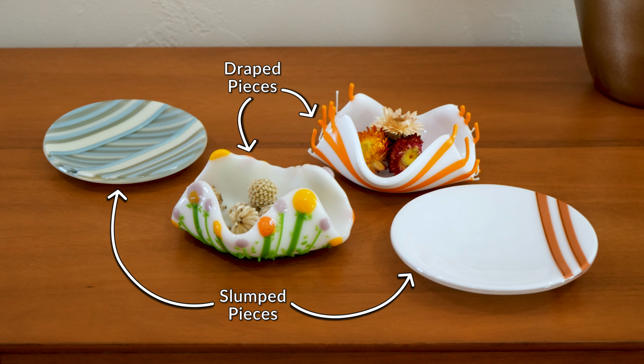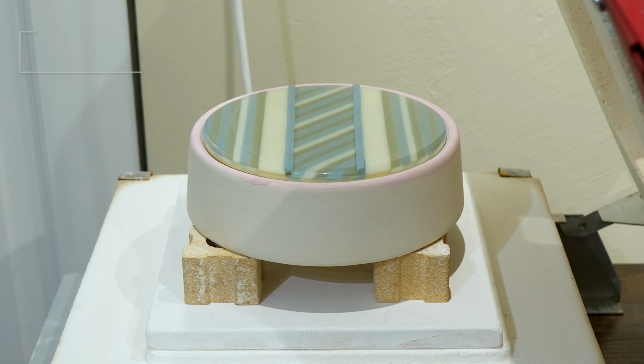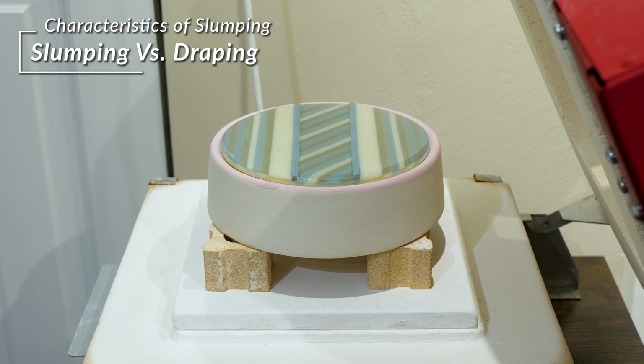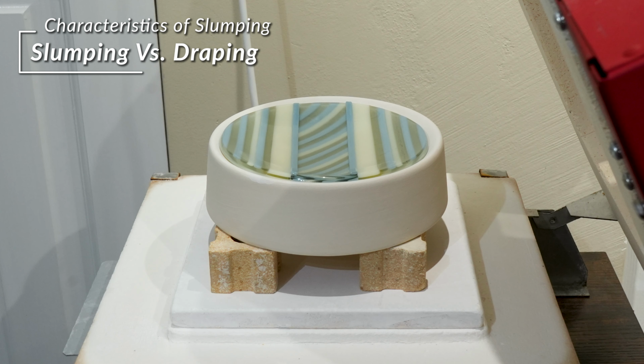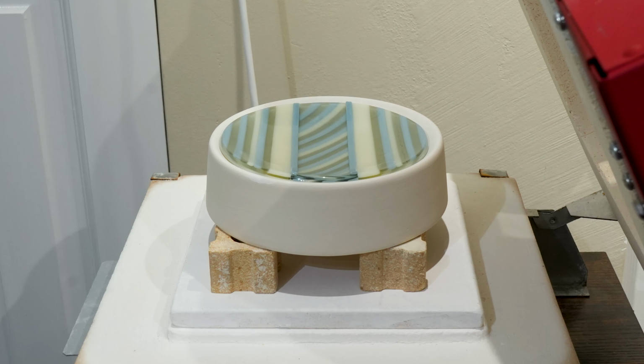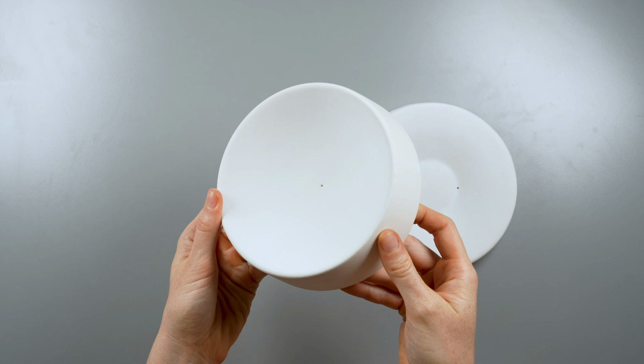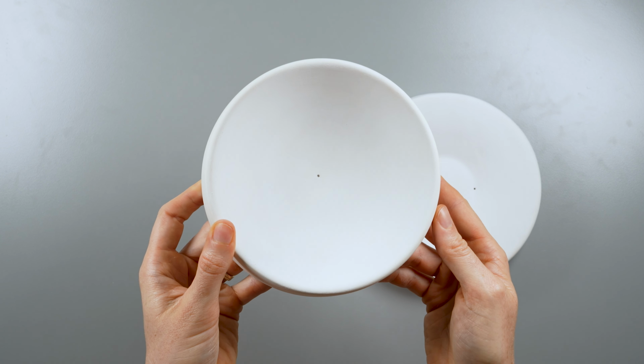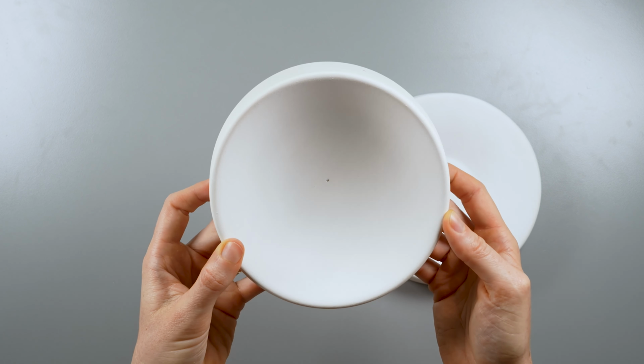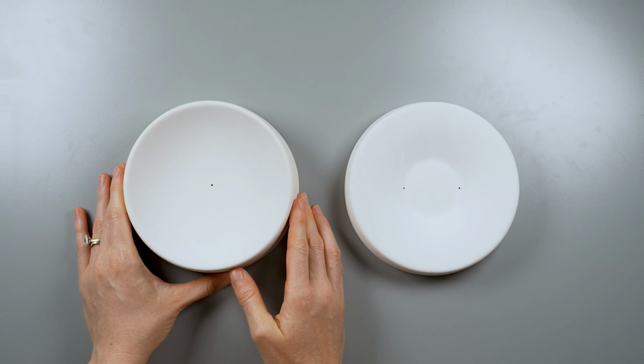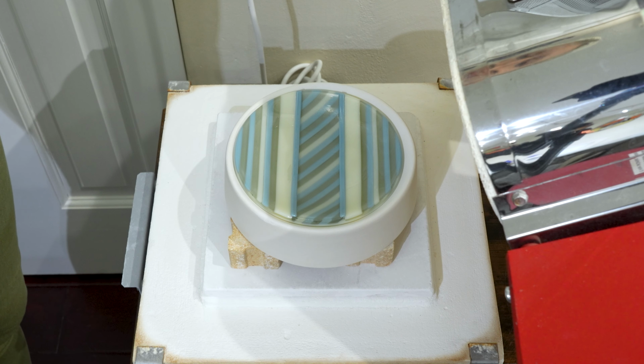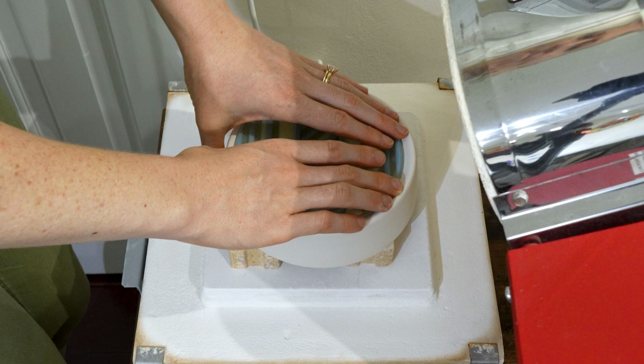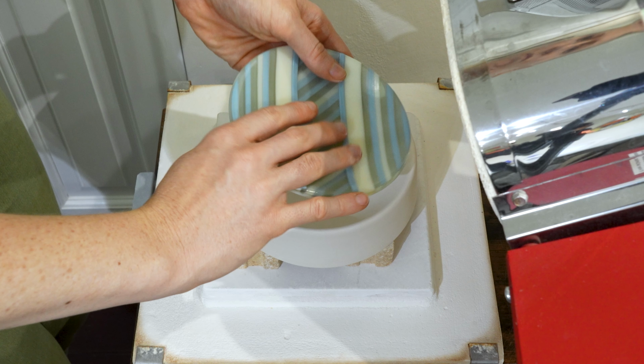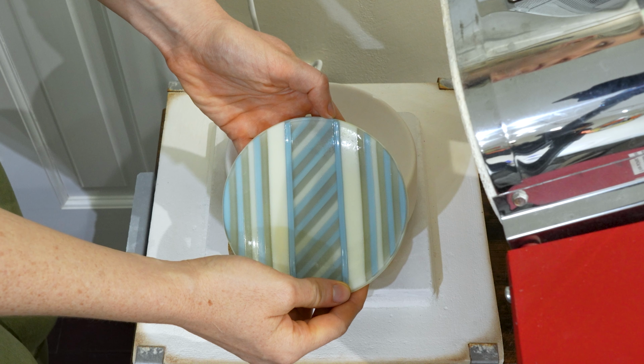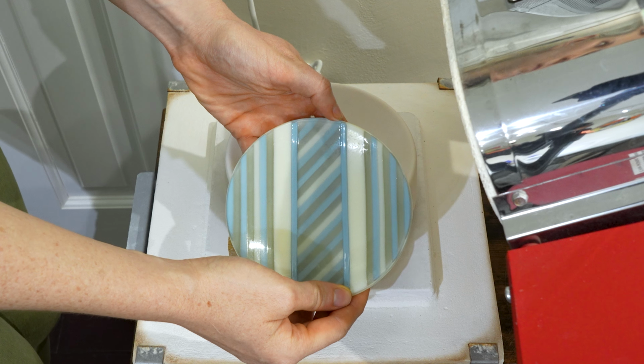Slumping and draping share a similar purpose, but there's a difference between the two. Slumping is when glass is heated over a concave form so that it drops into the form. Slumping is typically performed with ceramic molds because during firing, ceramic expands and contracts less than glass. This means that as glass cools, it can easily be lifted off of a concave ceramic mold underneath it because the mold has not contracted enough to hold the glass in place.